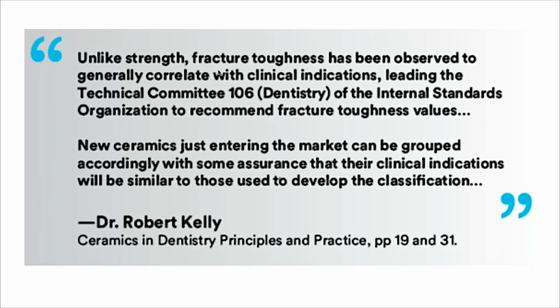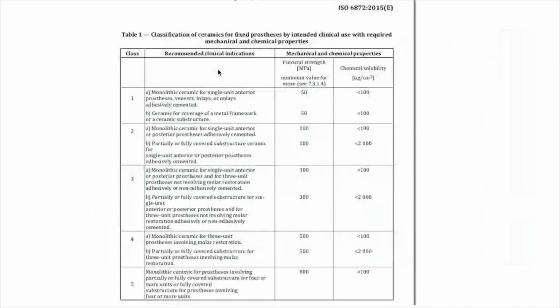This is where you see these ads everywhere that these materials have millions of megapascals in strength and all this business. So when you really do some testing, they're really not as high as some of these manufacturers claim they are, but most of them are still strong enough. The danger is if you put too much grinding and too much air abrasion on them, which can reduce the strength significantly. And I'll go over that later on in the presentation.